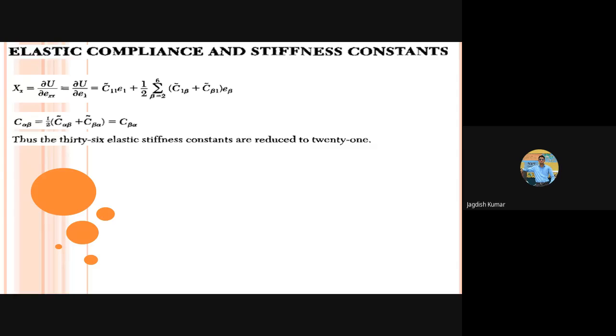Okay. So why is the number of elements going to 21? Now try to imagine a symmetric matrix. I hope you have studied symmetric matrices. What is a symmetric matrix? One for which the ijth element is equal to the jith element, isn't it? So there are a total of 36 elements as such, but when you impose the restriction and take the number of independent elements for a 6 cross 6 symmetric matrix, the number of independent elements should turn out to be equal to 21.